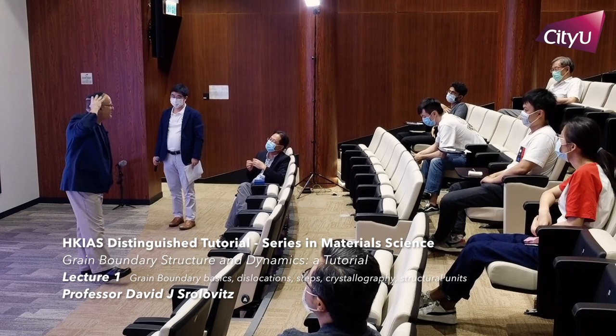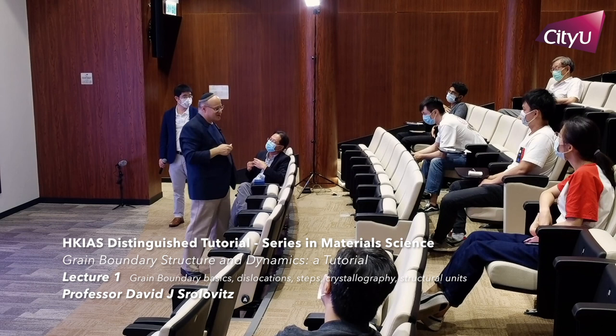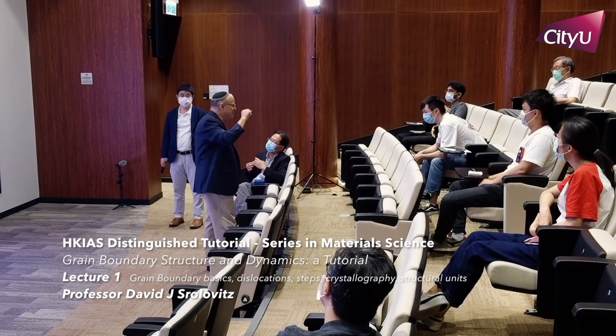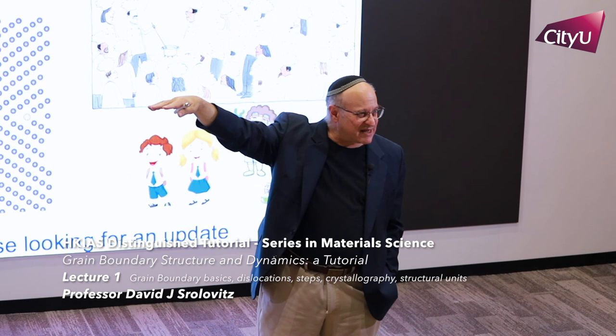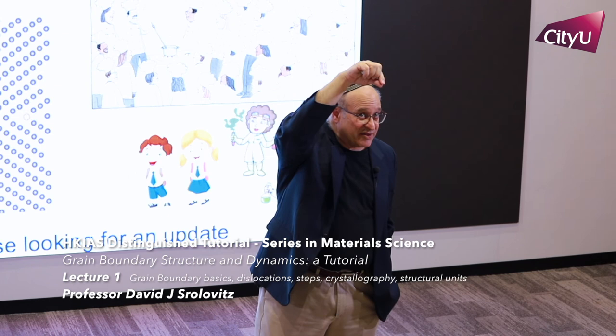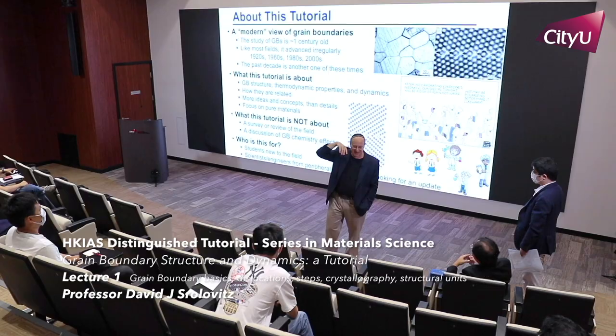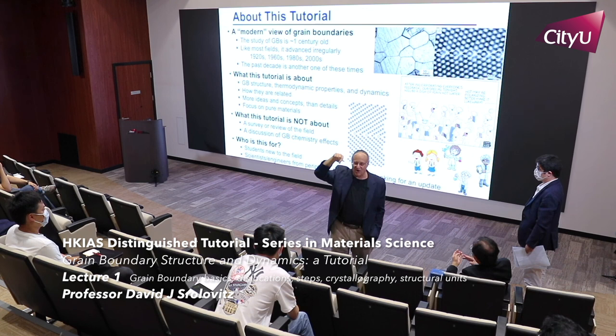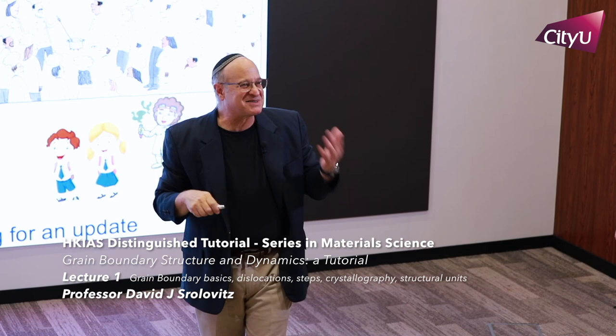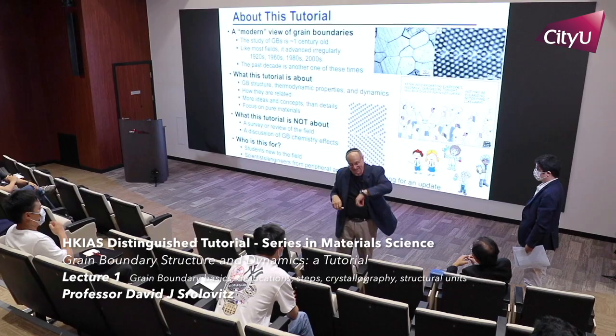The interesting cases are situations where you have interstitials. So you can look at segregation here by calculating what the energy of the solute is in each of those cores. But the thing that we haven't talked about yet, and I will start talking about next time, is you can also have metastable structures in grain boundaries. You can have metastable structures in a grain boundary by shifting the grain boundary this way. But the best way to get metastable structures is by allowing segregation.